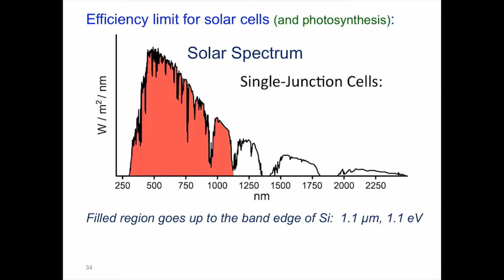So solar cells, and by the way, photosynthesis, are not very efficient. And the problem is that light comes in many colors. So here is the solar spectrum. The visible runs from 400 to about 700 nanometers, and there's plenty of infrared in the solar spectrum. And the shaded red area is the part of the spectrum we could capture with a silicon solar cell, which is out to about 1.1 eV, about 1100 nanometers.